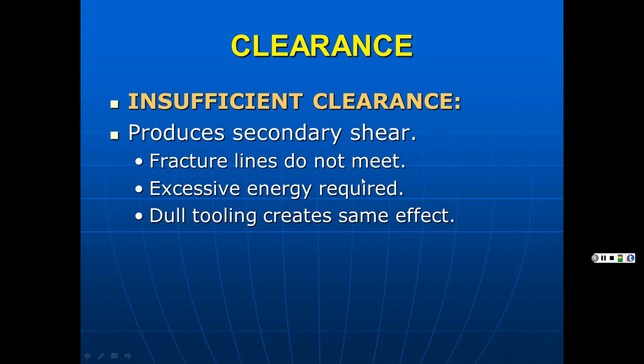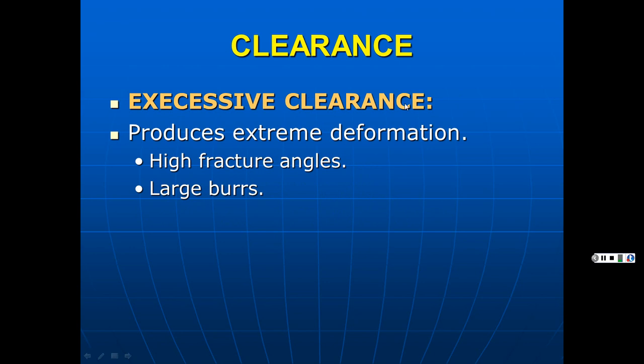And that way fracture lines don't exactly meet up right, and then you need more energy because it's not cutting like it should, and then because it's rubbing too hard, it's dulling the tooling, and then the dull tool makes it even worse and worse. Excessive clearance produces extreme deformation because you're stretching the material more before it finally rips. High fracture angles, large burrs that can cut people, or things just don't fit right because, let's say, it goes on somewhere else, but it's got this burred edge sticking up. So it's not good for assembly.